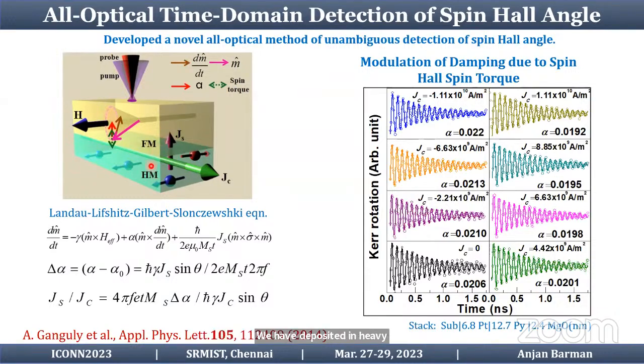Here it is cobalt and platinum, and using two electrodes we flow the charge current to the platinum layer, and because of the spin Hall effect, spin current will be injected into the ferromagnetic layer, and we induce the precessional motion. This spin current gives rise to a spin torque, which is given by the Landau-Lifshitz-Gilbert-Slonczewski equation. Here, this is the anti-damping like torque, which will act collinearly with the damping torque.